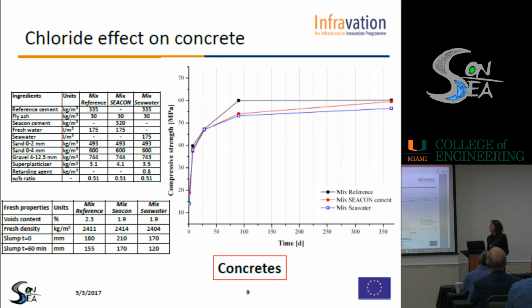Then we designed the different mix designs, three in this case: mix reference, mix SEACON, and mix seawater. The first one is the reference, with reference cement and fresh water. The second one is with SEACON cement and the addition of superplasticizer, and mix seawater needs also a retarding agent due to the acceleration effect of chloride. We designed them considering a fixed compressive strength of 45 megapascal at 28 days and also the desired consistency. You can see in the graph that in all the cases the compressive strength at 28 days exceeds our target, and that chloride has an effect at 90 days with a slight decrease in compressive strength.